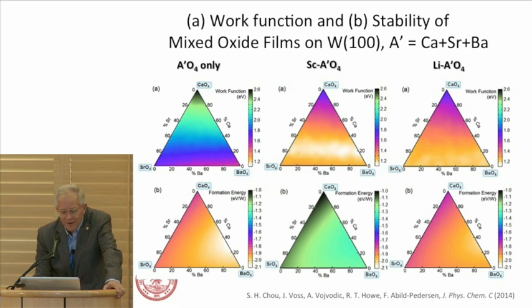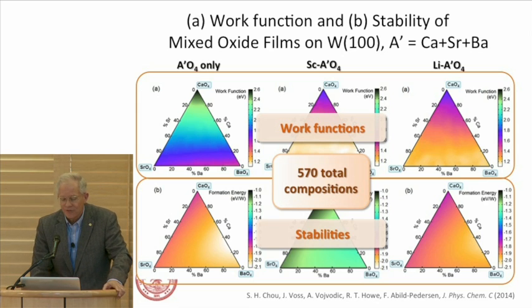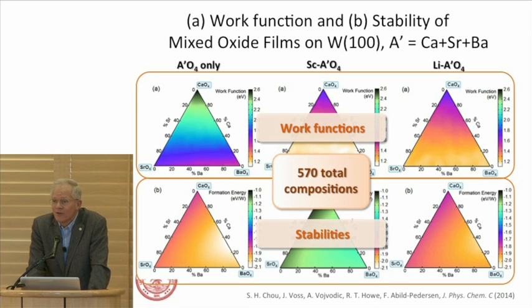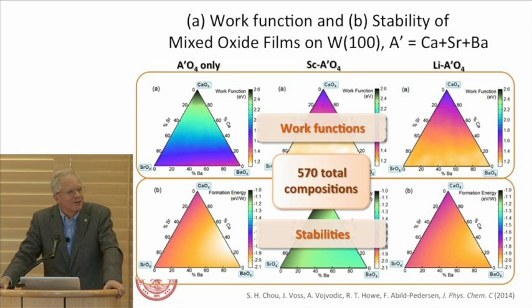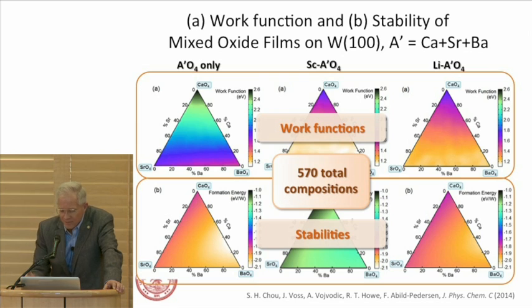What are we showing? We have the pure mixed oxides with all compositions, with work functions and formation energies, adding scandium and lithium doping. And this is work functions and stabilities, 570 total combinations. So what this does is short circuit a massive amount of experimentation. And at the Three Beams conference, which is where the electron beam people hang out, this is of great interest. They have been mining this for a number of years using technologies that are not as controlled as ALD.